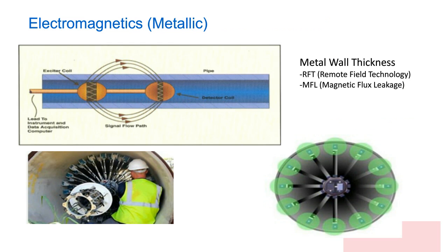So the type of inspections, the most common pipe, as we saw from the poll, was metallic piping, and that could be steel or steel riveted. And regardless of whether you're using RFT, which is remote field technology, or magnetic flux leakage, or it could even be RFTC, which is remote field transformation coupling, they all rely on the same technology platform, which is magnetism. And as you can see within the diagram here, what we're doing is we have an exciter coil and a receiver. And essentially what we're doing is we're sending a magnetic field through the wall from the inside to outside diameter of the metallic pipe.